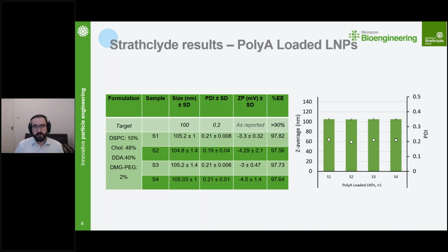So we set out to demonstrate that this was suitable for producing the type of particles that are required for vaccines, given that that was the immediate need: how can we help people to develop these vaccines from those small scale benchtop requirements to those full large scale production needs as well. So we started out working with the University of Strathclyde on some initial work to essentially target some representative lipid nanoparticles, looking at about 100 nanometers in size with very high encapsulation efficiencies, and the documented recommended PDI, which is the polydispersity index. Essentially lower is better, but 0.2 is typically the recommended level for near monodisperse there.